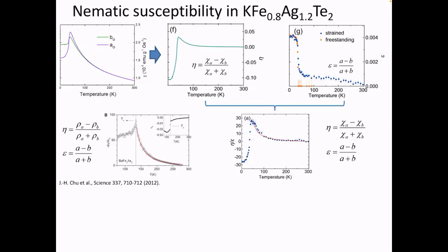But in the ordered state, it actually gives you a small susceptibility because all the spins are already ordered along that direction. So I think this is common to magnetic systems. This sign change actually provides evidence that the anisotropy we see above the transition temperature is due to fluctuations rather than static order. I see. Thank you.